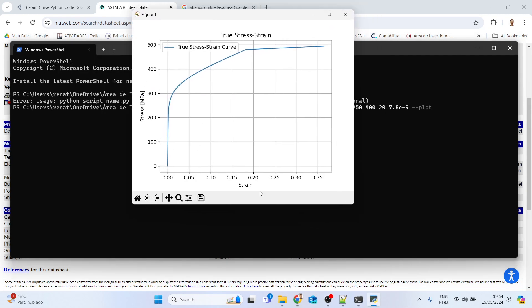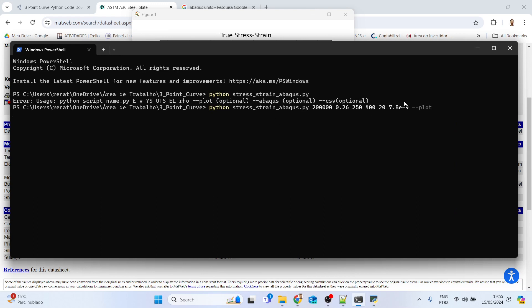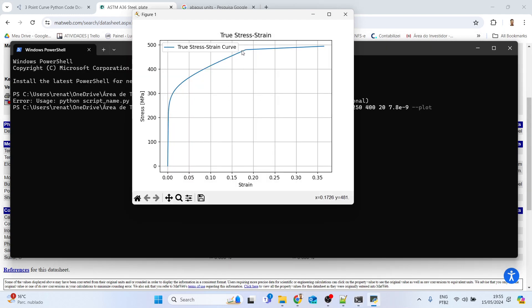Adding the optional argument --plot generates the stress-strain curve plot, with stress in MPa and strain dimensionless. You can see the yield strength and the UTS marked on the curve. This is the true stress-strain curve — the input was engineering stress of 250 MPa, and the script transformed it into true stress-strain. So at 20% elongation you don't get exactly 400 MPa as inputted.